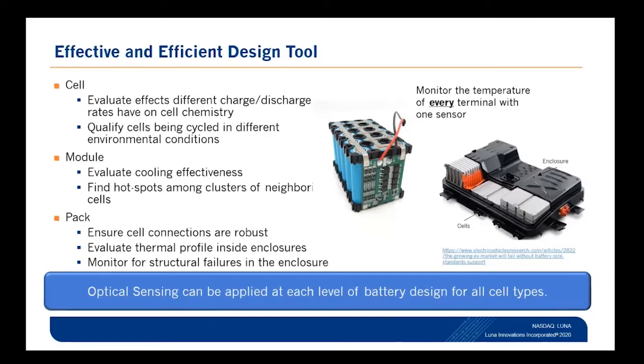When we look at it specifically in relation to batteries and using it as an effective and efficient design tool, it's applicable at all levels. At the cell level, it can be used to evaluate the effects of different charge and discharge rates, and what those will do to cell chemistry. As our keynote speaker had mentioned, cell chemistry is one area that has a very large focus right now, as folks are trying to combine the largest amount of energy density into the smallest space while also maintaining a high degree of safety. Fiber is inert in many chemical environments, and it's also non-conductive. So when you're performing charge and discharge tests on cells, which are damaging tests, it's a very good system to set up so that you can fully qualify what's going on both internally and externally to the cell as it's undergoing testing.